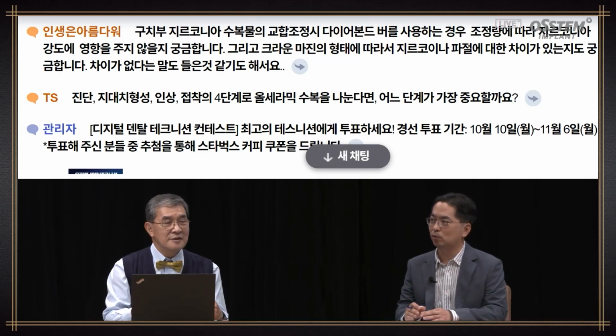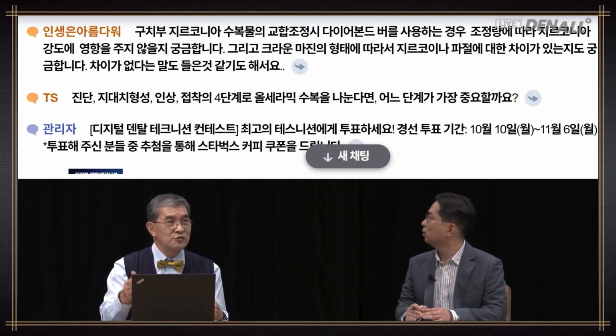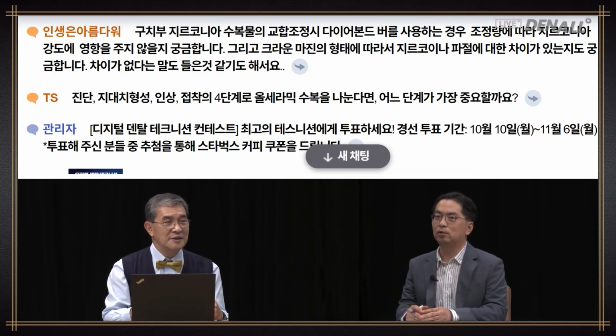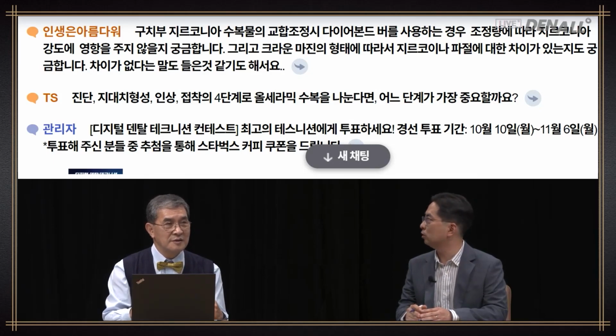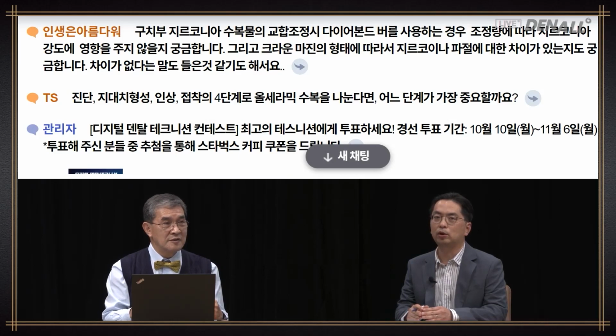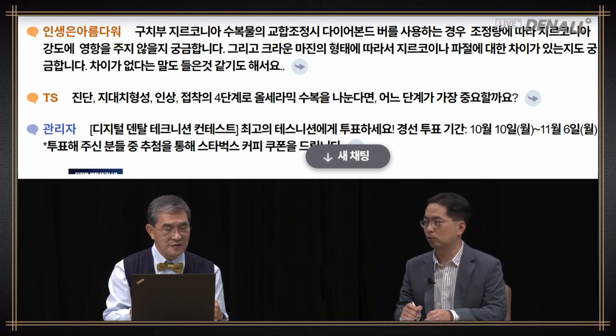I think polishing is more important. You need to do occlusal adjustment without generating heat. Do you need to do irrigation? Yes, you need to do it in order to reduce the temperature. You need to do occlusal adjustment with irrigation depending on the adjustment amount. If there's no crack upon adjustment, it will not affect the strength, but reducing the height itself means that the thickness is reduced. As a result, it will affect the zirconia's strength.